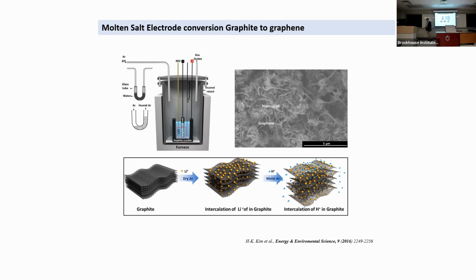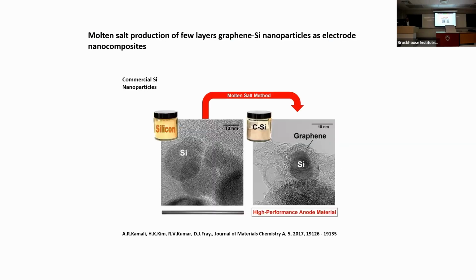So the advantage of doing that, not only you produce a graphene structure, for example, or nanocarbon structure, you can also embed silicon into the same carbon structure, like by using silicon oxide. It deoxidizes, and you get a combination of carbon and silicon. Now, silicon is mechanically otherwise unstable, but when it's encapsulated within these graphene planes, it becomes very stable. It is absolutely able to mechanically take the load. Otherwise, silicon, when it expands because lithium is reacting with it, it actually fractures during the charging and discharging cycles. Okay, so therefore, high performance anode materials can be produced, for example, by using this approach.